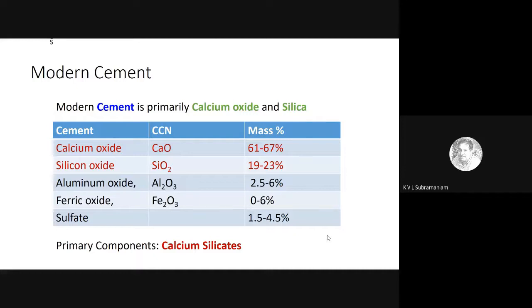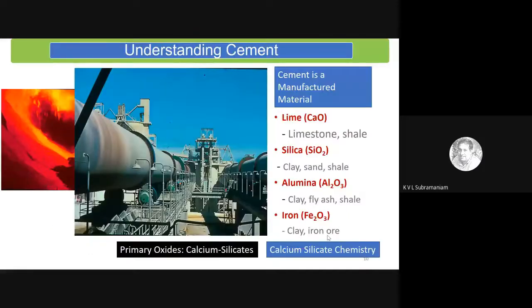So the calcium and the silica keep coming up again and again. And even in modern day cements, it's calcium and silica, and primary components are calcium silicates in cement. So basically, cement chemistry is all about understanding calcium silicate chemistry. Now, as I had mentioned before, in the manufacture of cement, therefore, if I have to produce a calcium silicate, I need sources of material that can give me calcium and silica. So usually, and this has not changed, if you look at the limestone, it's still the source that we use for the source of calcium.